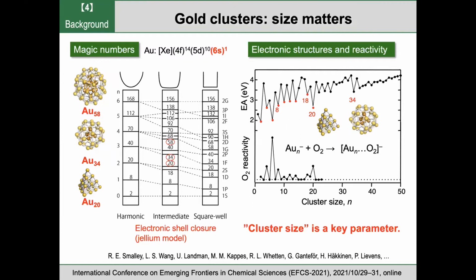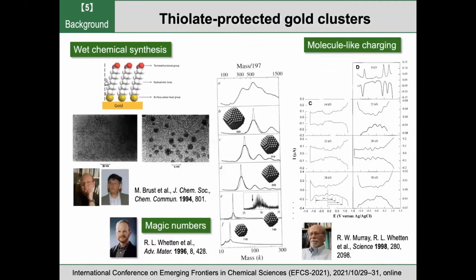Okay, so these clusters are isolated in vacuum. But in order to make them a chemical compound, we have to protect the surface with ligands to suppress sintering into larger particles. The most famous ligands we use are thiols, sulfur-containing molecules. This is because we know sulfur molecules spontaneously form a self-assembled monolayer like this on the gold surface. The gold-sulfur bond is a very strong interaction. This idea was applied to nanoparticles by Professor Brust and Schiffrin in 1994.